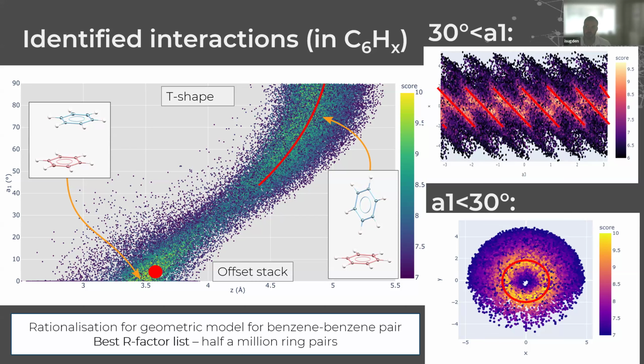If you look at the graph in the top right, this is for interactions where the A1 score, so the interplane angle, is greater than 30 degrees, so it's more T-shaped, and then we rotate around A3, so that's the donating molecule's own axis, and you can see it's a sawtooth mode where the molecules move away a little bit as the proton moves out of the accepting molecule's electron density, and then move back in as it keeps rotating around its axis. And so this is a six-fold interaction that's showing you the protons like to be placed in the electron density of the next benzene unit.